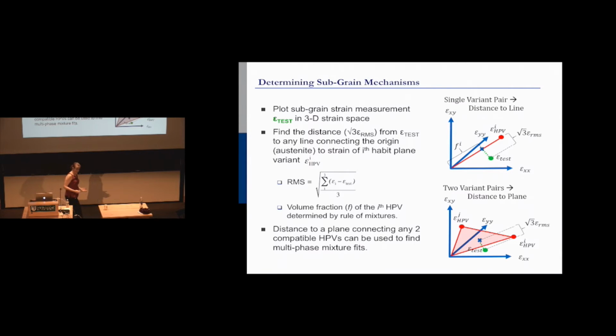So if you take all these data points inside a grain and you throw them into strain space, they actually cluster around certain shapes. They actually cluster along a tetragon. And the reason they do that is because they all relate back to a specific type of variant that introduces a specific type of strain. So you can imagine you take a strain data point and you plot it here. This is 0 strain. So this would be nothing's happening. You don't have any change from the austenite. The austenite is the reference. So you're fully austenite here. This would be, I'm 100% whatever that HPV is. The HPV is the purple layer cake. So that's going to give you a certain strain. You can calculate that. And then anything along here would be some combination of those two correspondent variants.